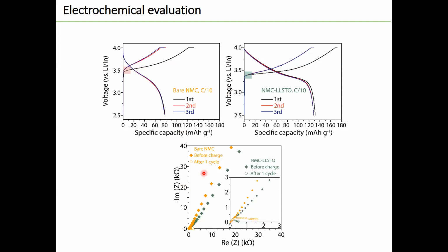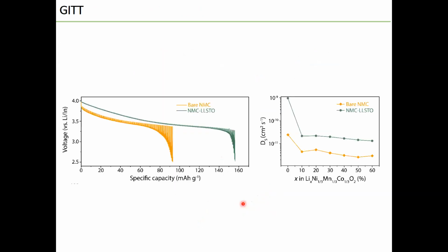We compared the impedance of both cells before and after one cycle. We can find after one cycle, NMC with coating exhibits much smaller charge transfer impedance. GITT was then performed to compare the ion diffusivity in both cathodes. It is obvious NMC with coating delivers a much higher capacity, around 156 milliamp hour per gram, which is close to the theoretical capacity. We can get the ion diffusion coefficient with the coating of LLSTO. The ion diffusivity was greatly enhanced.